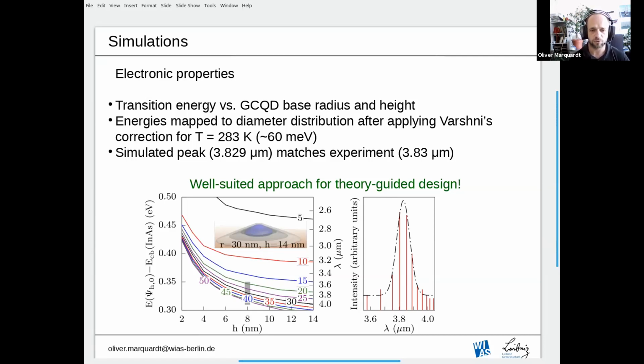And then we have mapped the respective energies from our simulations after Varshni correction and so on to this particular range. And this is pretty much the intensity peak we could see then. It has its top at 3.829 microns, which matches the experiment extremely well. So the experiment, I remind you, has 3.83 microns. So we believe we have found here a well-suited approach for theory-guided design for such systems.